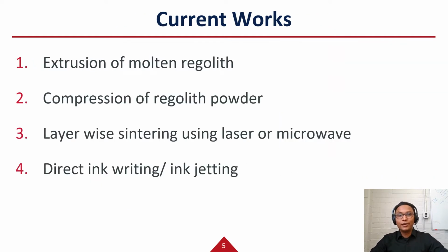To use the lunar regolith, researchers are exploring various 3D printing technologies that differ in terms of material pre- and post-processing requirements, machine setup, scalability, and autonomy of operation. For example, we can use lunar regolith with a liquid binder to form a paste that can be deposited using extrusion-based processes. Then the sintering process can remove the binder to produce dense parts. This approach is very straightforward, but also very effective in utilizing the regolith.